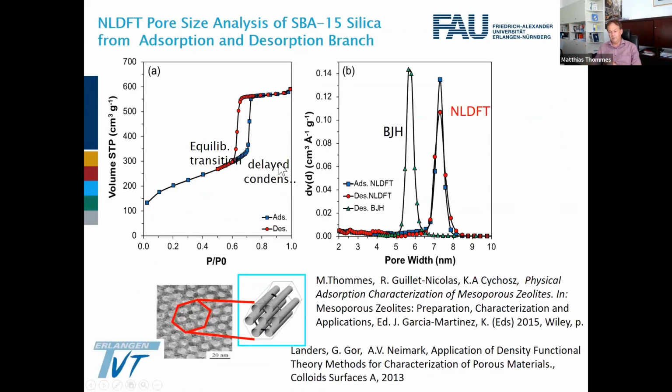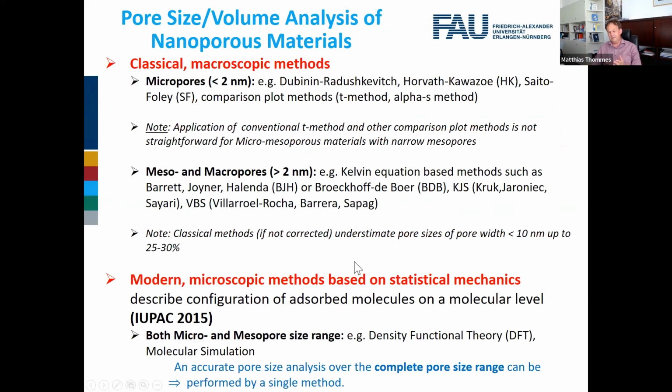And here's an example. First of all, I have to mention that the classical methods cannot, and this is now the connection to one of the initial slides, when we have reversible capillary condensation, the disappearance of hysteresis cannot be described by methods based on the Kelvin equation. So when you're looking at narrow mesopores, say below 20 nanometers, but particularly when they're below 10 nanometers, all these classical methods cannot accurately describe the adsorption isotherm and its correlation to pore size and geometry.